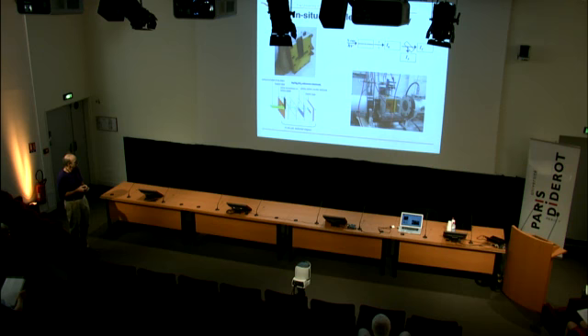We do our experiments at the Brookhaven synchrotron in upstate New York. And this is the cell. The main thing in the cell is that the DENs are immobilized on a carbon paper electrode. The problem with this experiment, this is a really hard experiment, is that there are not many atoms, not many platinum atoms, and not many copper atoms. So this is actually a very difficult experiment to do.